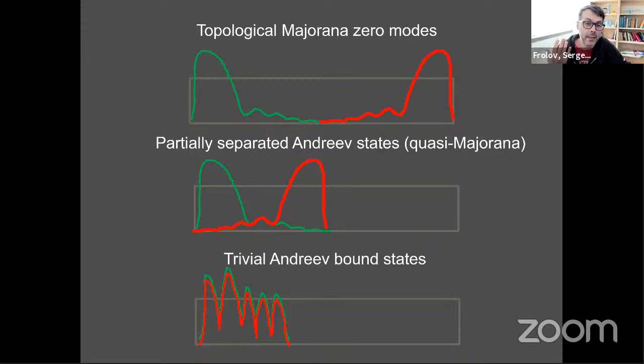Now, if we add things like disorder or finite wire size, then the green and the red wave functions may actually overlap significantly. So that's the middle picture. Well, it maybe still originates from the same physics, from the same four ingredients with spin orbit and superconductivity, but the system size is too short, and it is like a partially separated electron, or sometimes people say quasi-Majorana. So that's still interesting, but more difficult to unambiguously say that it's Majorana.